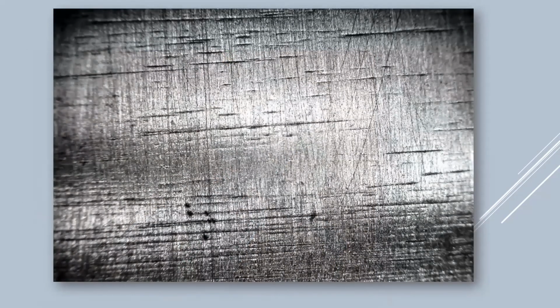This is a replica that I did. I'm not too proud to say, because when you look at this, I've got scratches going horizontally, big scratches, like 240 grit scratches. And you see some vertical scratches too. Those are from the 600 grit. So what's happened is I haven't removed the scratches from that coarser paper, and I'll never get rid of them. This is going to be an artifact on that client's replica. But there's one little area that doesn't look bad. I still gave it to the client because we had to get it done quickly, and there still was one little area where I could answer the client's questions. But scratches are an artifact.